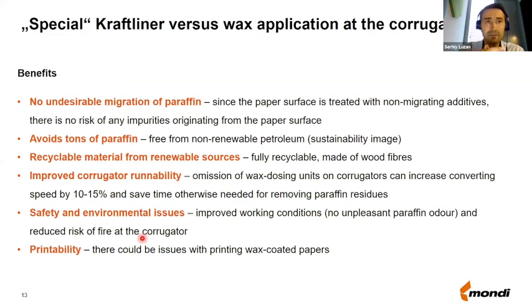And in some cases, this special treatment at the paper machine and the special kraft liner could be quite a viable alternative to the wax application at the corrugator. Here I'm not speaking about very extreme cases, where you simply immerse the piece of corrugated board into the wax, but I'm speaking more about the soft application where you apply some water repellent wax at the corrugator. You can achieve quite a similar effect with this special kraft liner, because this step of application is basically taken back to the paper machine, and therefore you don't need to use any paraffin at the corrugator, therefore avoiding some paraffin, and also adding to the, which is quite important now, sustainable image of your brand, of your company.